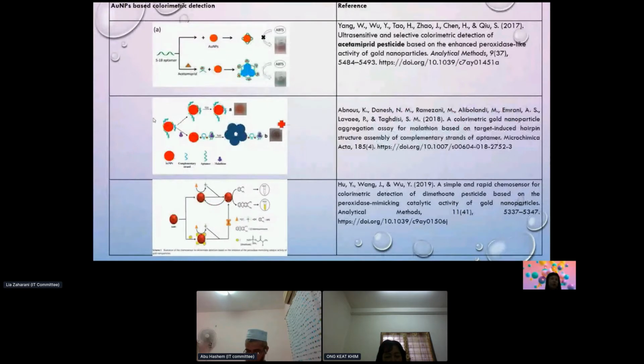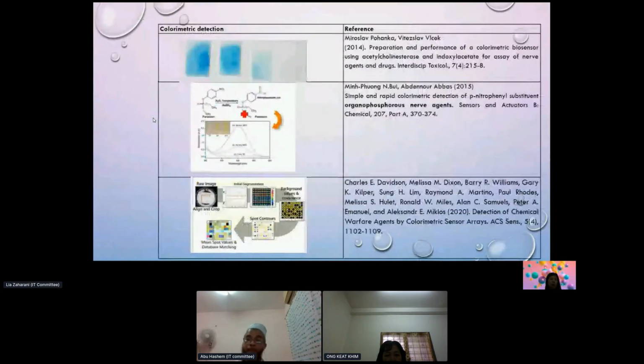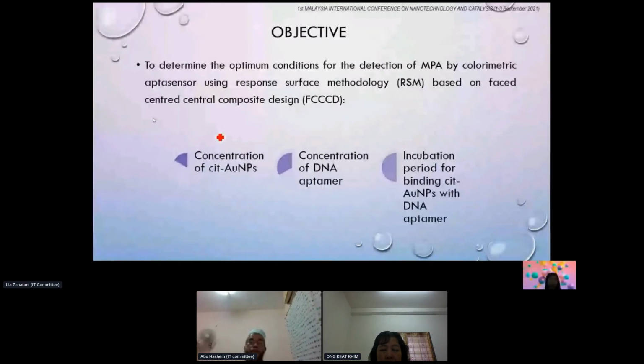This slide shows some previous studies using gold nanoparticle-based colorimetric detection to detect pesticides. You can see the color will change from red to blue or darker blue or yellow. Colorimetric detection is also used for detection of nerve agents or chemical warfare agents. In this study, they incorporate image processing techniques to improve the colorimetric detection accuracy. Therefore, the objective of this study is to determine the optimum condition for detection of methylphosphonic acid by colorimetric aptasensor using response surface methodology based on face-centered central composite design. There are three factors investigated in this study: concentration of citrate-capped AuNP, concentration of DNA aptamer, and incubation period for binding citrate-capped AuNP with DNA aptamer.